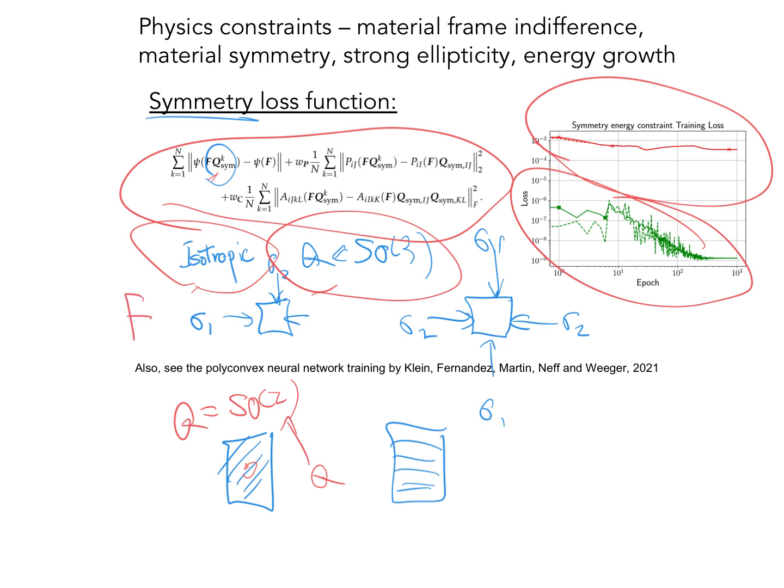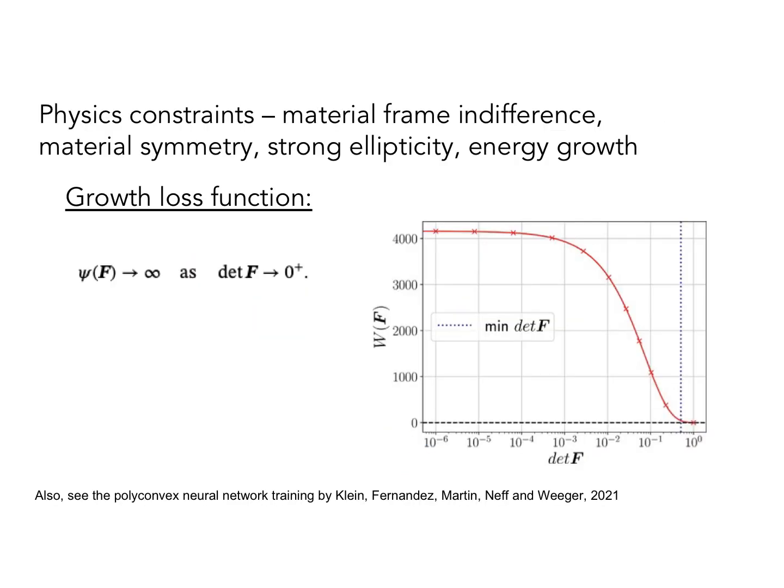So what are you going to do? You typically put the determinant of F as one of the inputs to write the energy functional, and then maybe you use the first and second invariants, or the first, second, and third invariants, to write the elasticity model. That is also another way of doing it. So it depends on whether you want to leverage the symmetry to reduce the dimensions or you want to add the constraint. To measure that, we may use the L2 norm. Okay, so far so good.